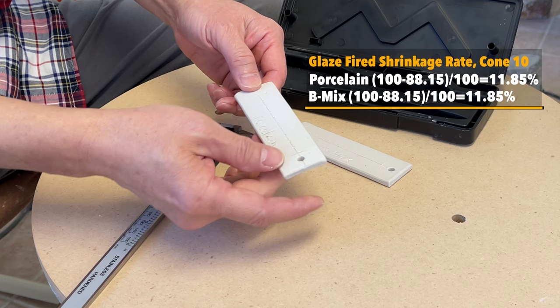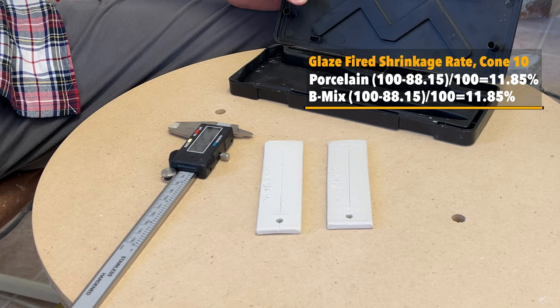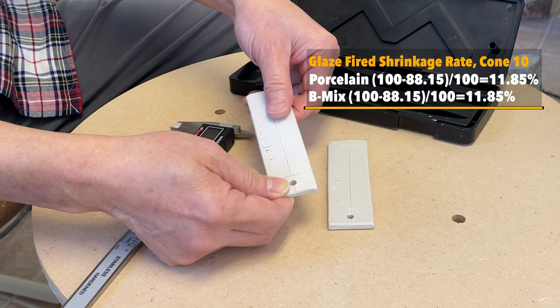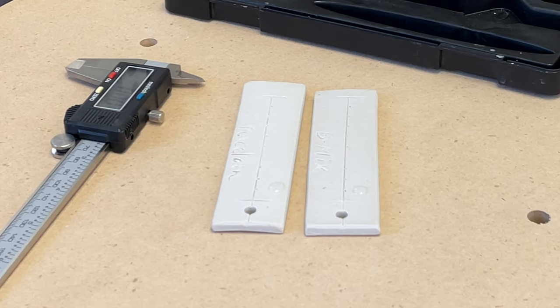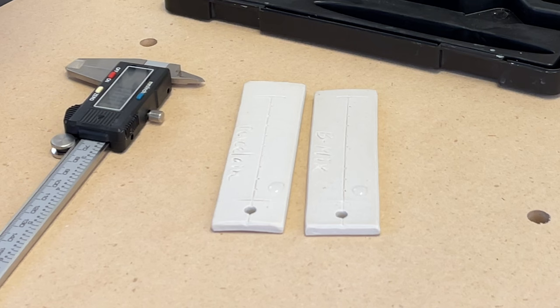You can test your own clay to know exactly what percentage it shrinks. Also, you can check if your clay is vitrified or not. Soak it in boiling water for some time, weigh it before and after soaking, and see the absorption rate. You can also put a drip of water on the test tile and see if the water soaks in or stays beaded — that's another vitrification test and you don't need to boil water for five hours.